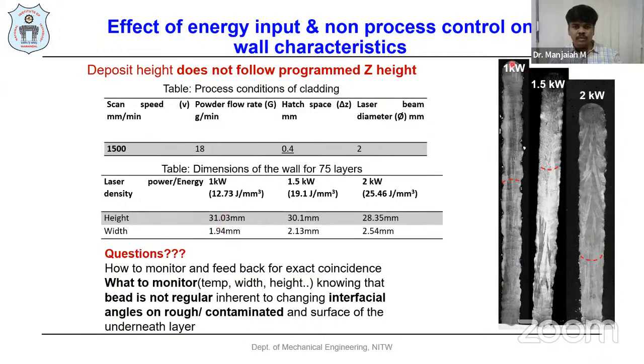For example, for 1 kilowatt, we are having 31 millimeters of height with the width of 1.94. And for 1.5, we are having 30 millimeters, 2.13 of width of the layer. And for 2 kilowatt, we are having 28.35 with 2.5. Means the height is decreasing and width is increasing as we are supplying more energy density. Because if you are not optimizing the energy density to get the required layer width and height, then it definitely will affect the geometrical defects.